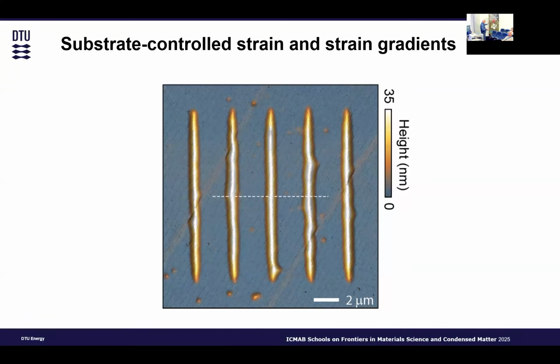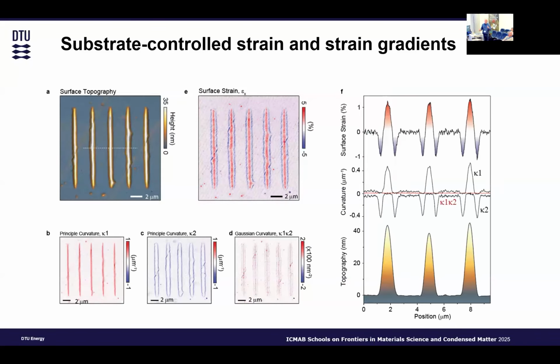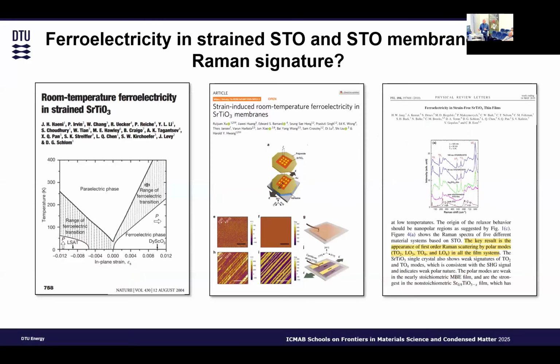It just conforms all the way over these membranes, over these nanowires. So we measured the strain, and here we could get from our calculation a strain of about 1% at the top. So it's not huge, but we know at least where we are, what we will look for. So it's a 1% strain.